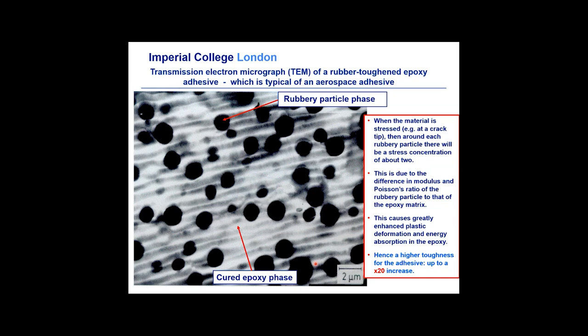This is a transmission electron micrograph of a rubber toughened epoxy, which is really one of the mainstays of the engineering adhesive range. It's typical of an aerospace adhesive. What we have is the epoxy. Ignore the black lines, they're just chatter marks when we are sectioning the sample, but what we really are seeing is the cured epoxy phase, and then the black spherical particles are the rubber particles. They're about 1 to 2 microns in size, as you can see. There's usually about 10, 12, 15% maybe by volume of such rubber particles. Now, the presence of the rubber particles means that when the material is stressed, at a crack tip, for example, there will be a stress concentration of about 2 around their equatorial plane.